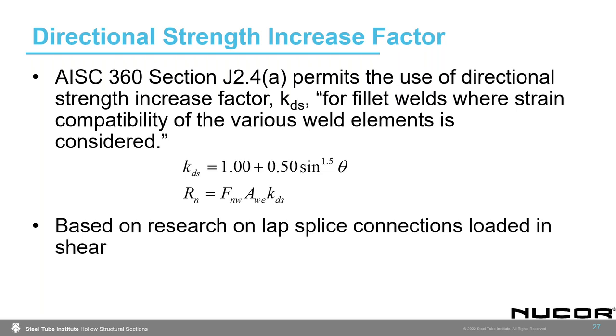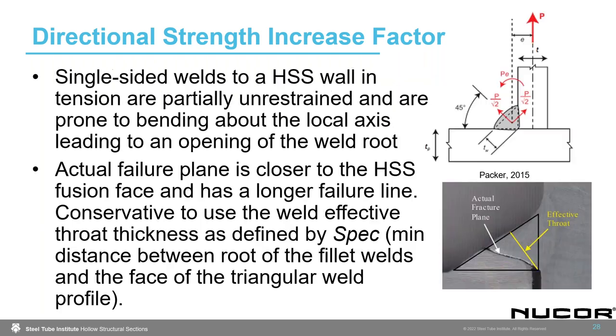So this is what the specification states: that we can increase the strength of a weld by a factor that ranges from 1 to 1.5 for fillet welds where strain compatibility of the various weld elements is considered. Going forward, what we've found is that single-sided welds to an HSS wall, which is specific to HSS because we're almost always dealing with single-sided welds, when they're in tension, are partially unrestrained, and you can induce some bending about the local axis leading to an opening in the weld root, as you can see in the diagrams on the right-hand side.